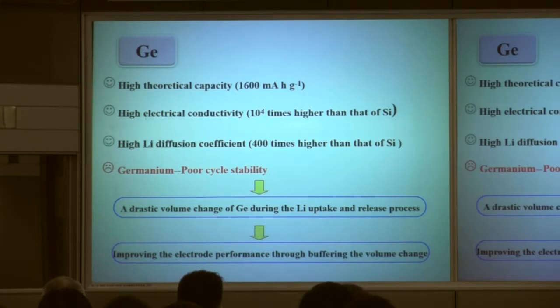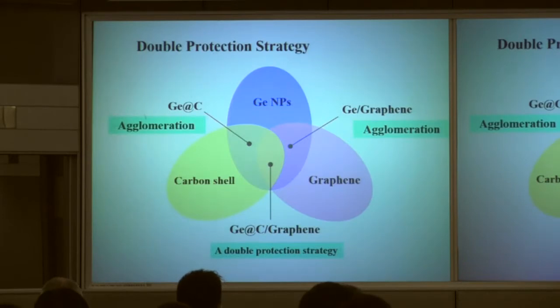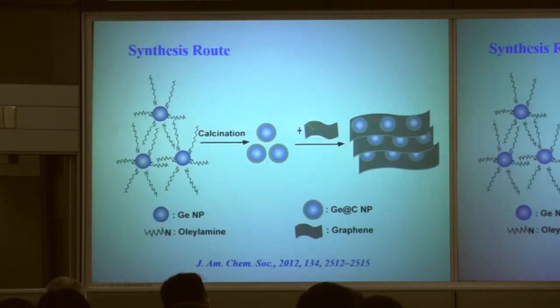So how to get a high capacity, high electrical conductivity, and also a high lithium diffusion coefficient, and a very high cycle stability? We try to make a composite material. We call it the double protection strategy. So first, we cover the germanium nanoparticle with carbon. After getting this carbon composite material, we then put this composite in graphene layers. So after the double protection, the new composite material will have a very good cycling performance. Here is the main story. First, cover our germanium nanoparticle with carbon, and then put this carbon in graphene. Okay.